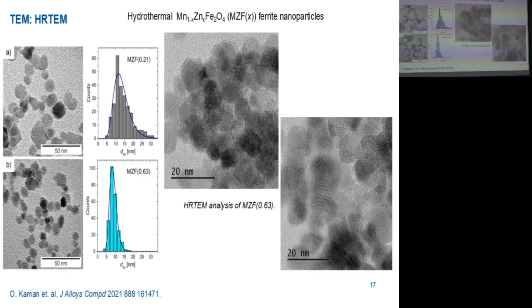So let's go to another technique available in transmission electron microscopy, and that's the high resolution imaging. Now it's quite common that people have access to high resolution transmission electron microscopy. So it's very useful to go to large magnification and to see your particles in more detail. For example, these micrographs are from the normal mode of transmission electron microscope, like from lower magnification, and if you enter the high resolution mode, you can see some very nice details like these patterns. They are called lattice fringes, and they are directly related to crystallinity because they arise as the result of constructive interference of the transmitted and diffracted beams. So this is a manifestation of electron diffraction, and it proves the crystallinity of your particles.